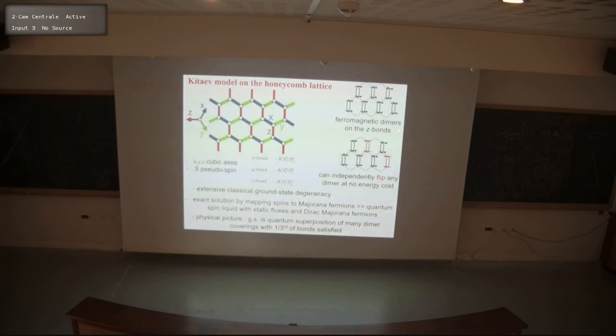So that's the best you can do on bonds like this, because you maximize the Ising exchange along this bond. The gray bonds actually carry zero energy, because the spins are aligned along the wrong direction. Now, let's imagine that we take one of these ferromagnetic dimers and we flip it. Okay? There's no energy cost in doing this because these still remain ferromagnetically aligned and these bonds carry zero energy. Essentially, we can pick any ferromagnetic dimer and flip it independently of anybody else. And this is the reason why we get an extensive degenerate manifold of ground states.